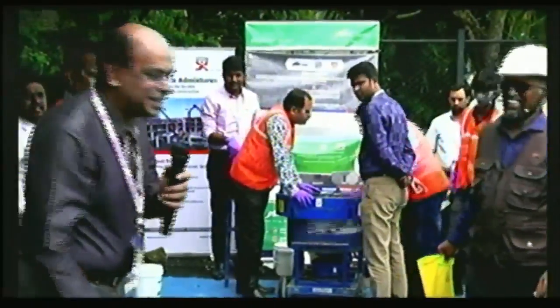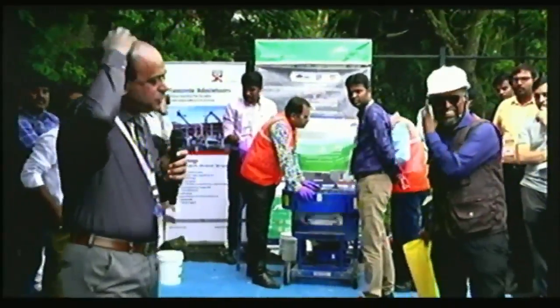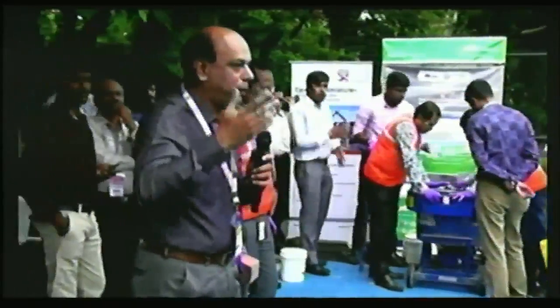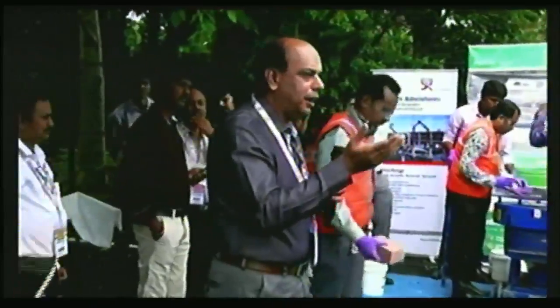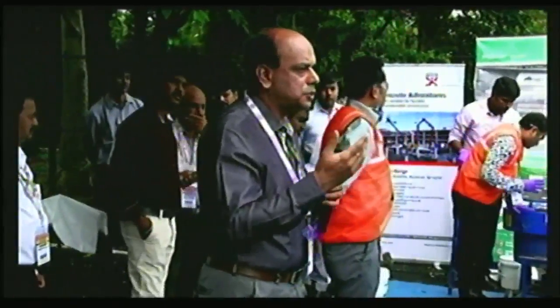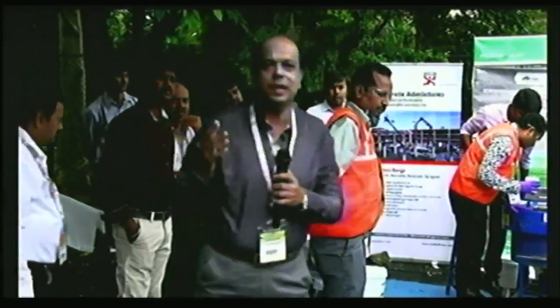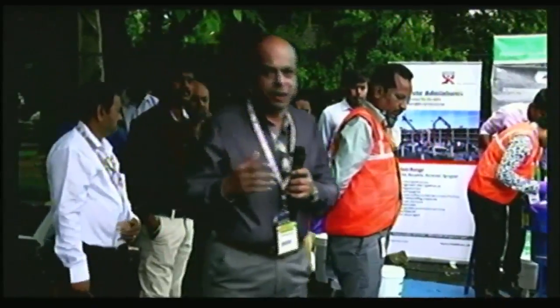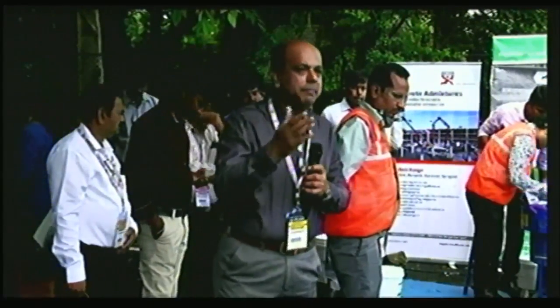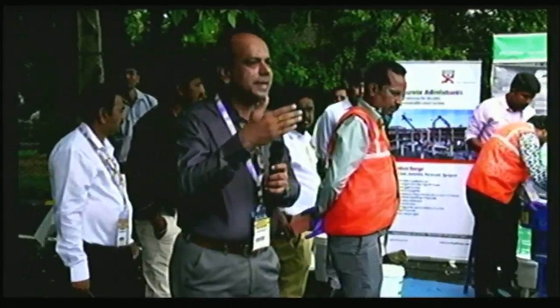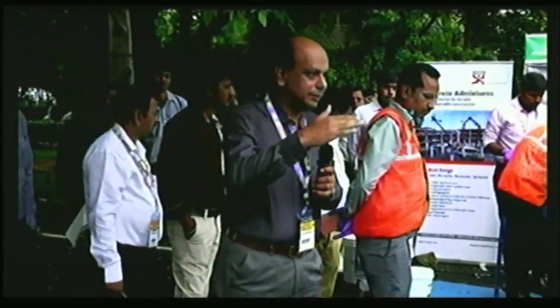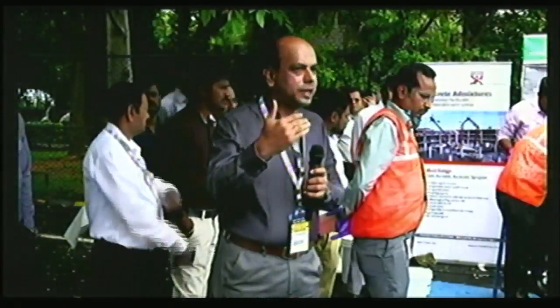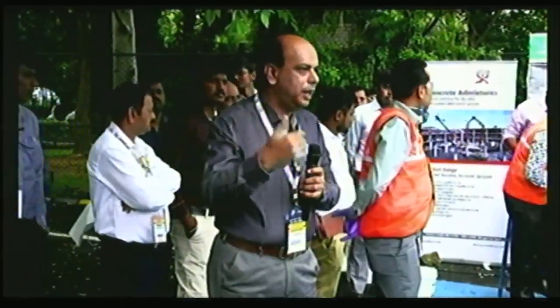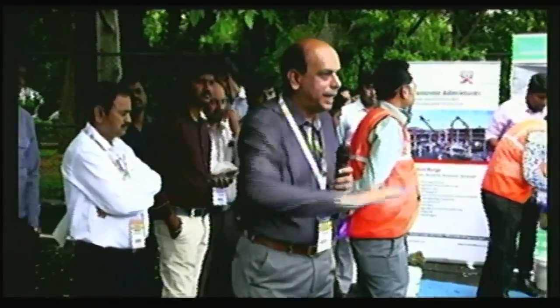Yeah, okay, go ahead, Shiv Prakash. Very good question. Basically, we just want to understand which is contributing to the flow. Obviously, we have done a trial even without admixture also. When we did the trial without admixtures, the slump was only 20 initially. So it's a very dry slump, because we wanted to compare whether the admixture is playing any important role with respect to strength. Admixture is definitely playing a major role in getting this flow of concrete.